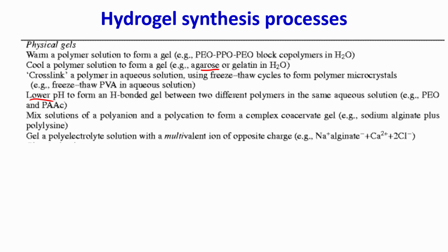Another one that is very widely used is the alginate gels. What is done is sodium alginate, which does not form cross links because it only has a monovalent cation. But then if you drop it into a solution containing calcium, what will happen? Let us say I have a beaker that contains calcium 2 plus, and I make a drop of the sodium alginate and let it drop. The sodium will leave the system and calcium will go in because it has higher affinity, it has a 2 plus positive charge, and so this drop will immediately polymerize to form a hydrogel of alginate. So, that is another way you can form these physical gels.